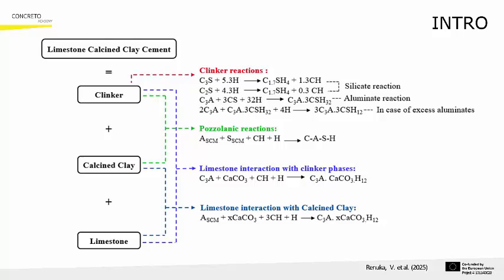Besides the pozzolanic reaction between calcined clay and portlandite, which produces additional C-S-H, two other reactions occur, one between the calcined clay and the limestone, and another one between the portlandite and the limestone. These two reactions produce mono and hemi carboaluminates, which further densify the microstructure.